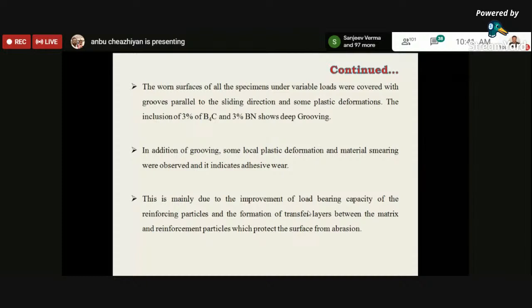So again, it is concluded that the worn surface of all the specimens under variable load were covered with grooves parallel to the sliding direction and some plastic deformation. The inclusion of 3% boron carbide shows deep grooving when compared to 6% and 9%, which show grooving, some plastic deformation and material smearing, as I told earlier, and this is due to the load-bearing capacity of reinforcement. The formation of a transfer layer between the matrix and reinforcement protects the surface from abrasion.